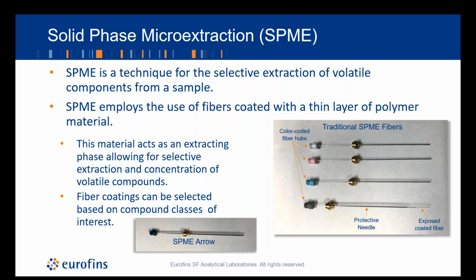And we can select fiber coatings based on the compound class of interest. In addition, we can further tailor this approach by changing the chemistry of the sample itself. For example, adding high concentrations of a salt solution to promote volatility, or changing the pH to target acidic or basic compounds.